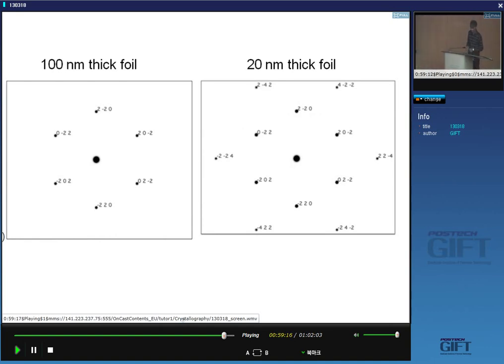This is to show you the thickness effect, that if I make my crystal thinner, then there's a greater chance of not satisfying the Bragg condition, but greater chance of picking up diffracted beams simply because the reciprocal lattice point effectively becomes extended more as you make your specimen thinner. So this is when we have a 100 nanometer thick foil. I only pick up these spots. If I reduce the thickness to 20 nanometers, I get a lot more spots because you can imagine each reciprocal lattice point as being extended normal to the plane of the foil.